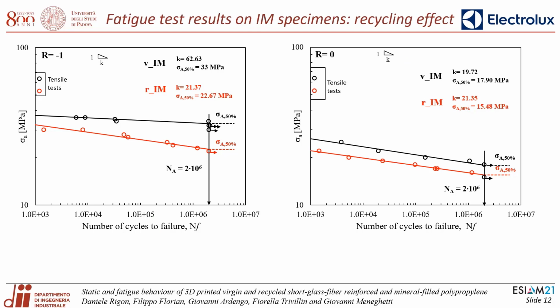Let's now have a look at the fatigue test results on injection molded virgin and recycled specimens. On the left, you can see the S-N curve in double log scales, reporting the results of the fatigue tests with load ratio equal to -1, while on the right, the results relevant to the tests with load ratio equal to 0. Sigma A is the stress amplitude of the cyclic load, and in the figure, the black points are related to the virgin compounds, while the red ones refer to the recycled specimens.